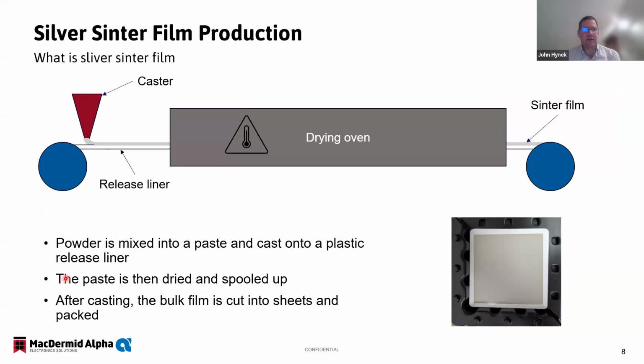So going to the next slide, let's talk about silver film production and what the difference is between a silver film and a silver paste. When you're producing a silver sinter film, the first step is you're taking the same silver powder that was made into paste with a paste product, and you're mixing it into a paste. This paste, though, is specifically formulated for casting. So the next step is you take that paste, put it into your caster here, and cast it onto a plastic release liner. The release liner is there to essentially hold the sinter film until you need it for use. That sinter film on the release liner is then put into a drying oven where it's very, very well controlled to drive off all of the solvents and everything else that makes a paste. So you're left with only the sinter film.